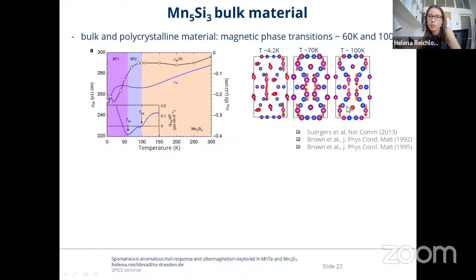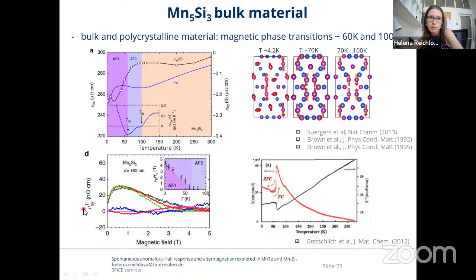In the polycrystalline films, the focus was on the low temperature magnetic phase. And in the low temperature magnetic phase, a nice topological Hall effect was observed, which is somehow correlated to this non-collinear character of the spin arrangement. And it's shown here, and it's present until 60 Kelvin when it disappears.